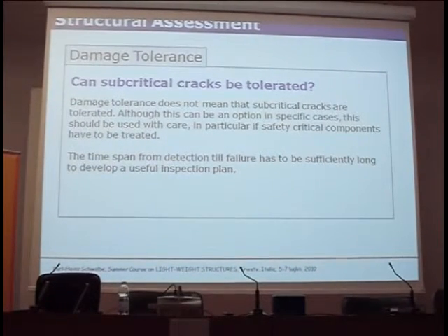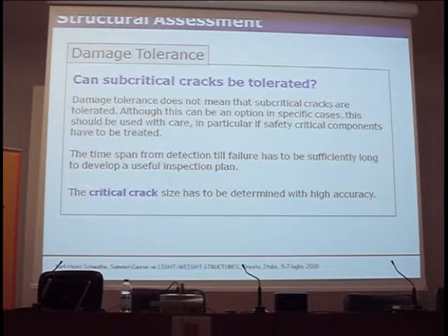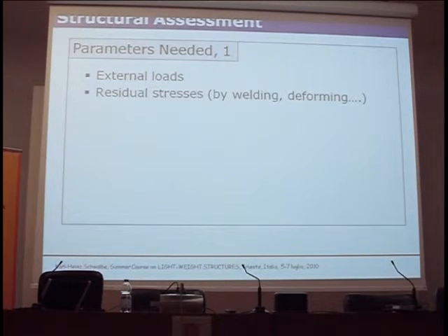Yeah, the time span from detection till failure has to be sufficiently long to develop a useful inspection plan. We'll see details later. And the critical crack size has to be determined with high accuracy. Now there's a number of parameters that we need. It's the applied loads, of course, residual stresses. There are several sources of residual stresses which are often ignored. And for many failure cases, residual stresses are blamed because nobody knows the exact magnitude, so of course, residual stresses. I'm not joking, this is reality.